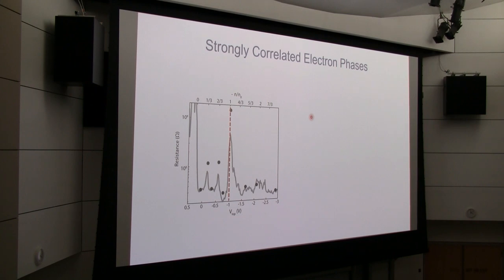So we are able to measure the effective resistance as a function of carrier doping. And we see that it shows a very non-monotonic behavior. So when you add the electrons, the resistance first decreases, then it shows some very strong resistance peaks. The strongest peak that we see corresponds to a density of 1 hole per Moire lattice site. So that's exactly 1 hole per period. So that's what Mott tells us. This is a Mott insulator.